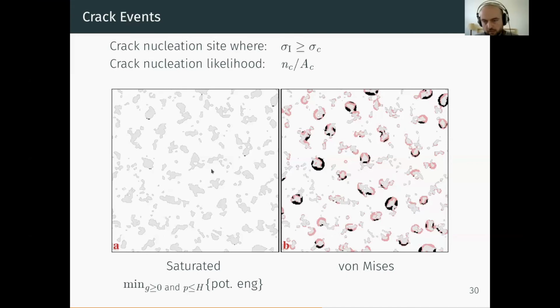And you can already see in black here the zones where this condition is satisfied. So those are the crack nucleation sites. And hopefully with the video compression, I'm not sure it shows up, but you have some black pixels here on the left. But on the right, you have many, many more crack nucleation sites with a full description of plasticity, whereas those are the same normal loads and the same yield stress. In red, you also have the plastic zones, which actually reach the surface in this case.